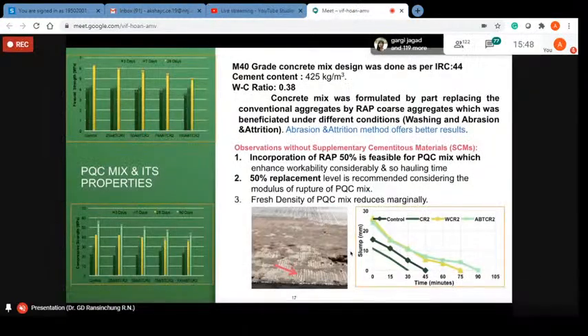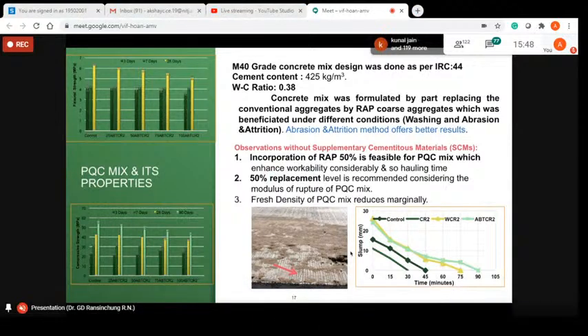And a water cement ratio of 0.38 was adopted. Then the concrete mix was prepared and the study was conducted for the different beneficiation methods. When I say different beneficiation methods, washing is one of the methods we have adopted, and the abrasion and attrition method is another. Here we are not considering the chemical beneficiation methods. From these, the abrasion attrition method offers better results. Therefore, we have decided to adopt this method for the further course of action.